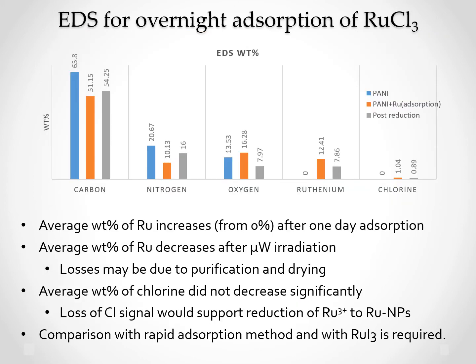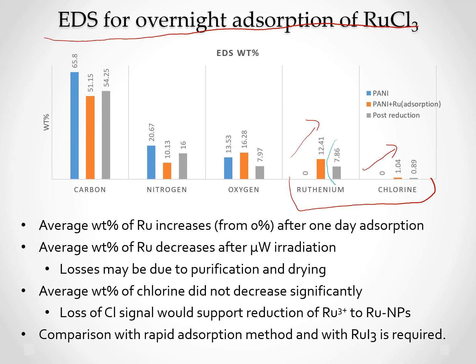EDS analysis for overnight adsorptions of ruthenium chloride — we focus on ruthenium and chlorine weight percentages. The ruthenium concentration increases with overnight adsorptions, as does chlorine. However, after the reduction, the ruthenium concentration decreases, which may be due to the purification process.